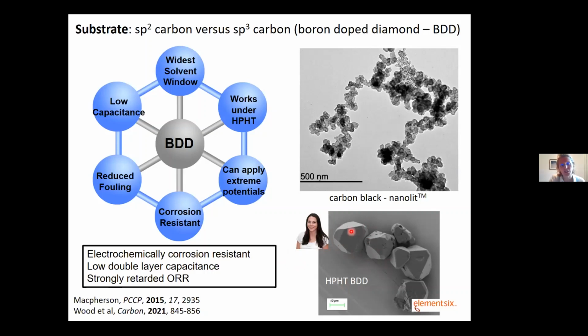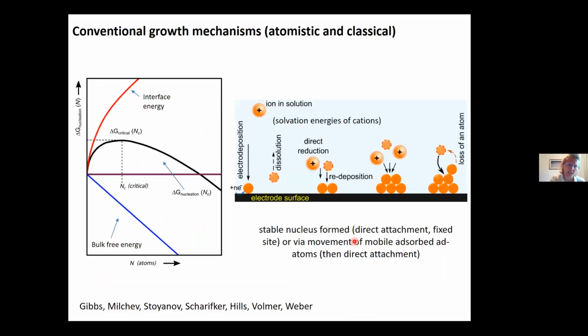And it's actually really challenging to get enough boron in using this mechanism of growth so that you can go into the metallic regime, which is what we need to make the boron doped diamond for an electrode process. However, I digress. So if we're looking at trying to kind of tame electrodeposition as a word, we need to try and look at understanding the growth of it and the nucleation mechanisms of metals on electrode surfaces.